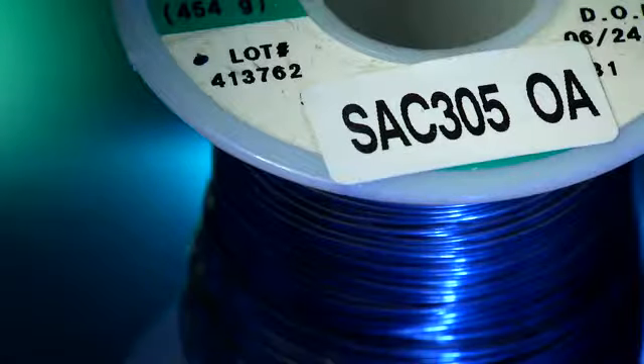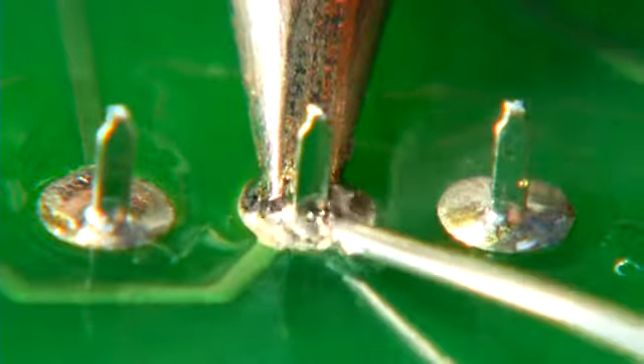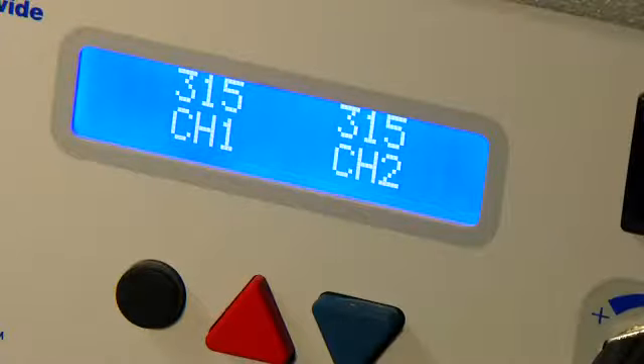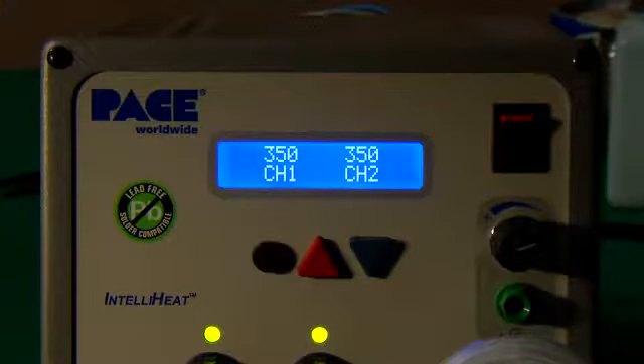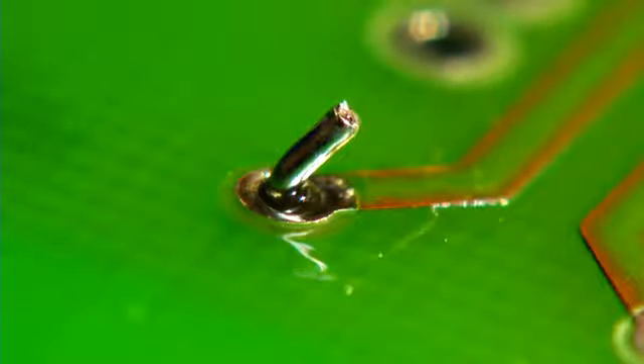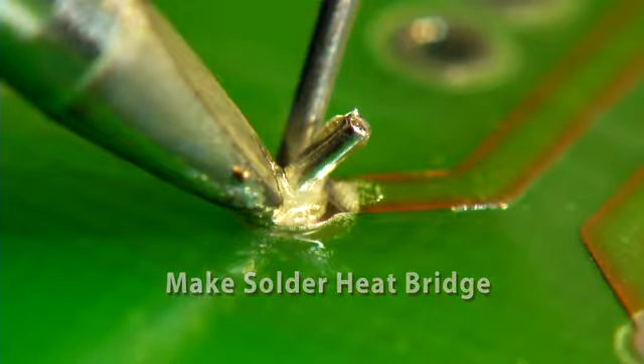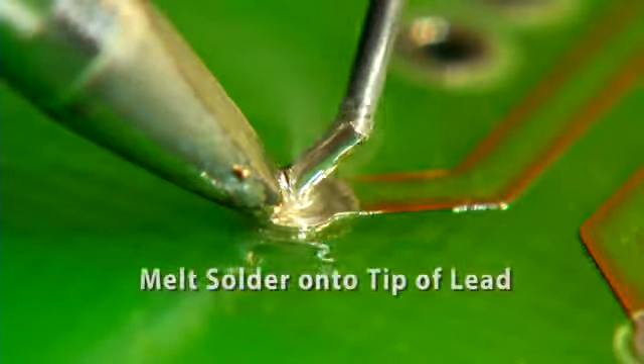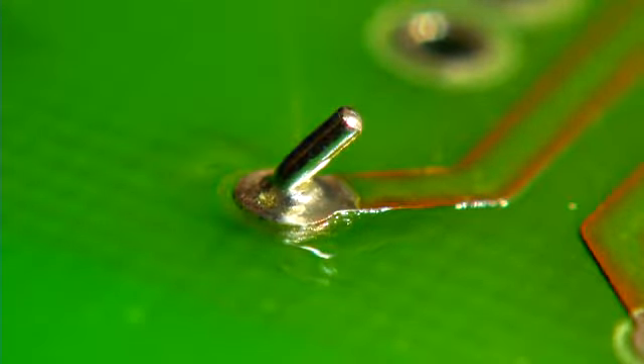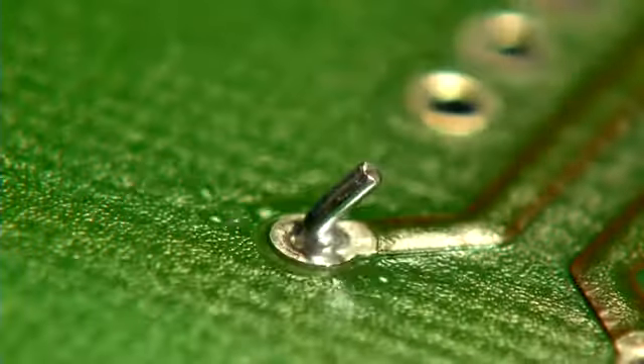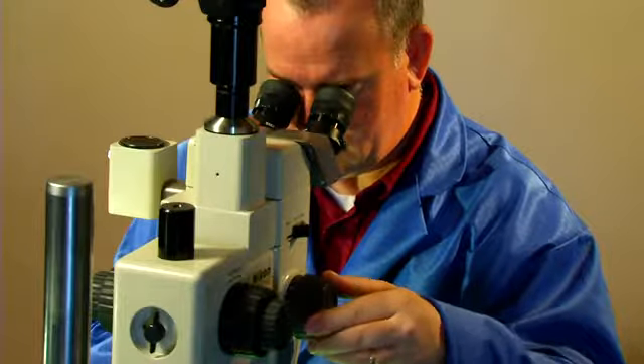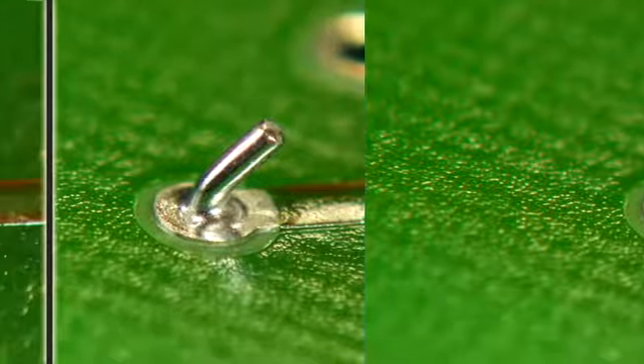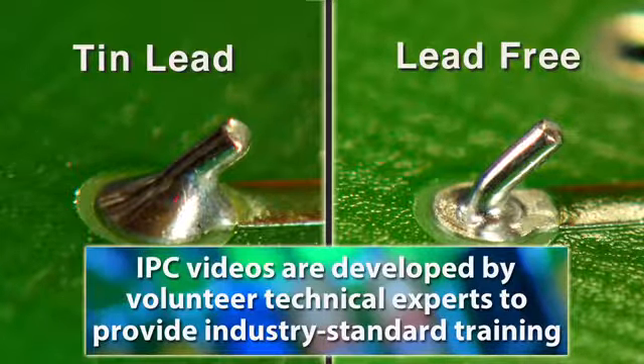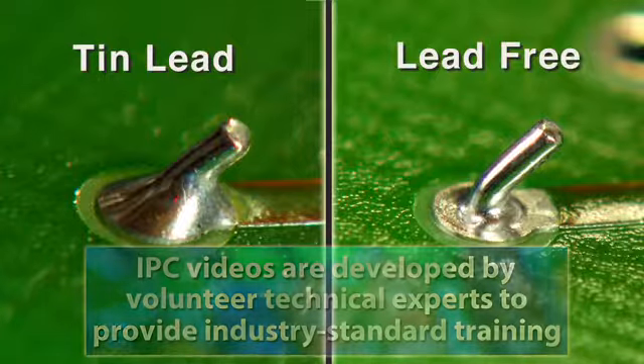Now we'll demonstrate the same soldering technique using lead-free solder. The main difference is that lead-free has a higher melting temperature than tin lead. So instead of a starting temperature of 315 degrees C, we'll set the temperature at 350 degrees C. Let's watch the soldering operation. Again, we clean the connection if required. The same inspection criteria will be used to determine a target solder joint. However, notice that the tin-silver-copper alloy is grainier in appearance than the tin-lead solder joint. This graininess is caused by the higher melting temperatures and is considered to be only a cosmetic issue.